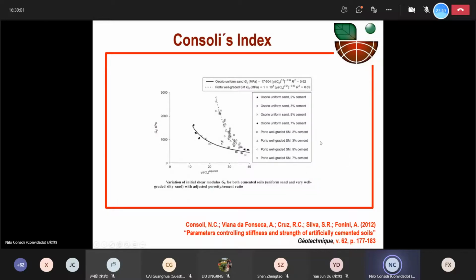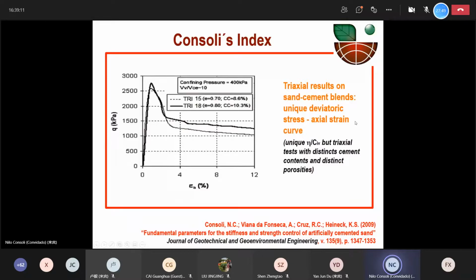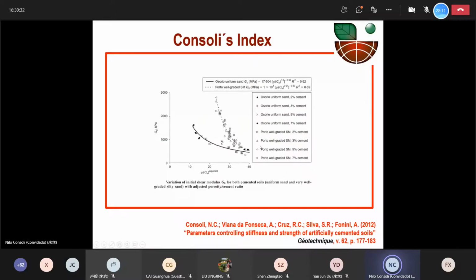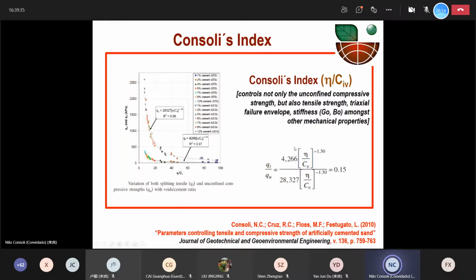For different amounts of cement and different soils, each soil has a specific curve. It's important to realize that you can get unique curves for each specific soil and each specific cement, varying the amounts of cement and also the compaction effort or the void ratio. Another interesting thing we can realize from these curves is that you can get a specific strength, for example, by varying the amount of cement or lime and the density.